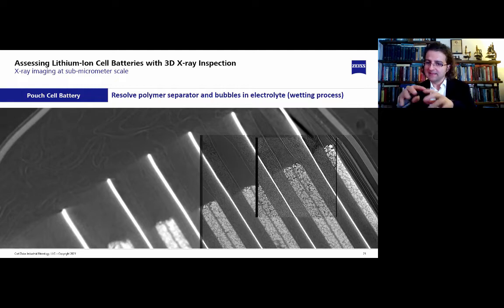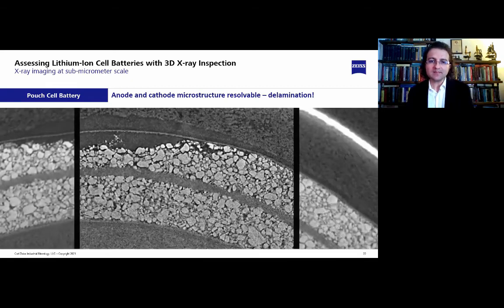There are obvious dense structures of the cathode and electrode that you can see, like the thick white bands, the anode current collector, the white stripes, and battery pouch casing, the perimeter, which all are detailed in this image. But the most impressive part is, of course, zooming in to see the granular microstructure of the graphite anode, as well as the mixture of lithium cobalt oxide in the cathode. You can clearly notice anode and cathode microstructure that is giving you very resolvable features and even trails of delamination in this image.